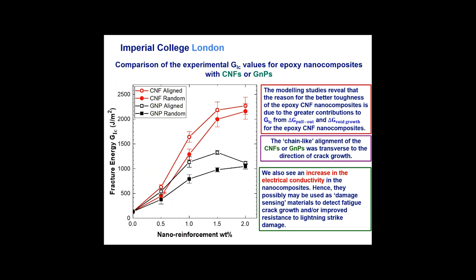You can see that the carbon nanofibers in red are more effective than the GNPs, the graphene nanoplatelets, in black. This is because we get more pull out and void growth associated with carbon nanofibers. We've published this work and we can model it theoretically as well.